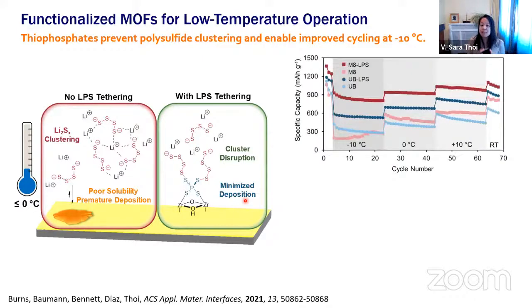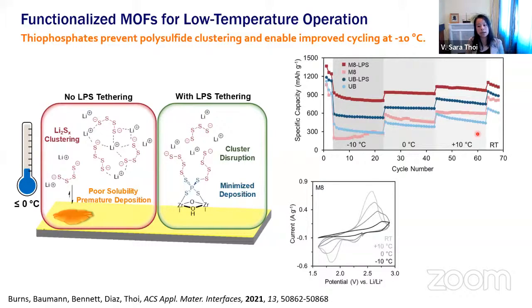And indeed, using the same LPS material that I've shown earlier, we see that in both cases, our functionalized MOF 808 and our UiO-66 material do indeed outperform the unfunctionalized materials at low temperatures. In fact, at all temperatures that we've shown here. This is interesting because it goes back to what we saw with the charge rate capability tests. What we see here is that using CVs, cyclic voltammetry, we observe that the unfunctionalized metal-organic frameworks have the pretty typical 2 reductive features for sulfur and 1 oxidative feature for sulfur oxidation at low temperatures and at room temperature.